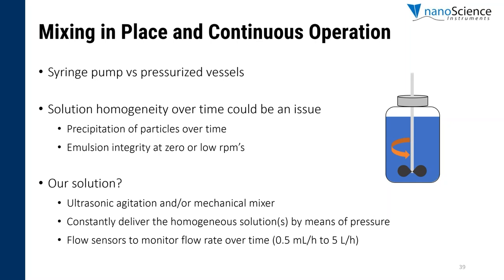In order to know the actual flow rate of the liquid flowing through the pressurized vessels, we can implement flow sensors that measure the flow rate as low as 0.5 mL an hour and all the way up to 5 liters an hour. So just for clarification, with our pressurized vessel, we can use a gas to push that liquid through the lines and then just make the electrospinning or electrospray happen. But since we're doing that, we don't know the exact flow rate that is going on depending on the pressure you're using. So we can implement those flow sensors in the line to make sure that we know the flow rate. If you would like any detailed information about any of these capabilities based on your application needs, feel free to contact us after the webinar.